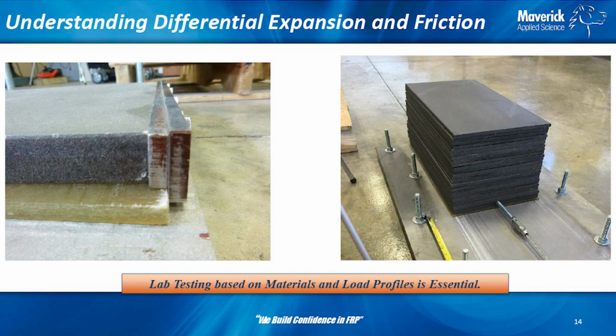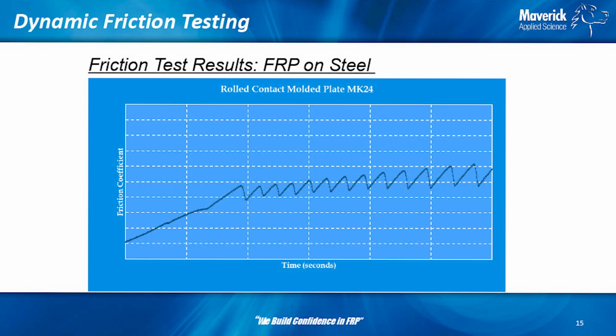So we actually made a sled here with an FRP panel on the bottom, made to a certain roughness on one side, and actually did friction testing. We pulled it across a defined steel plate, like what we would see in the process. We looked at what the friction was, and each of these plates represents about a foot of liquid. So we looked at it at different liquid levels as well, so that we could understand all the aspects of what was going on here. And this is what a dynamic friction test looks like. You go from static here, and you're pulling, and it resists, and then you hit a point, and all of a sudden it gives, and you see this kind of effect after that. So this is what a result might look like, to give you an idea.